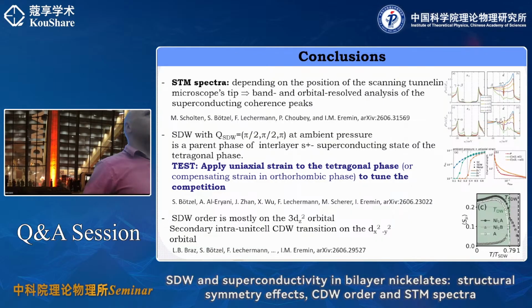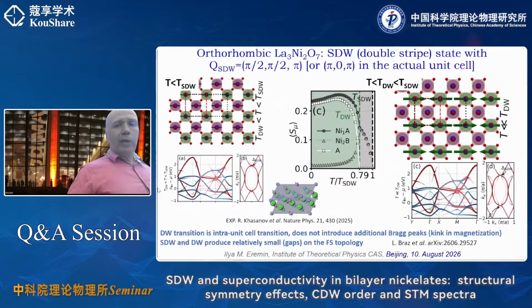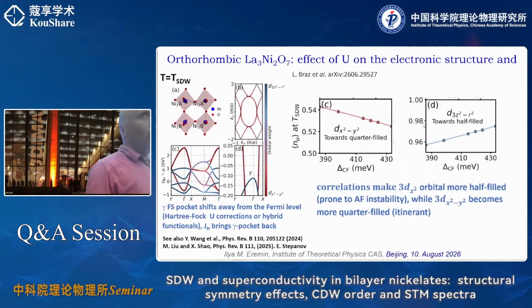But again, this is because, remember what I told you, and this is maybe something I can say, that this is more like a strong coupling picture: if you assume that the dz square is more localized, then of course you think that the main interaction is a super exchange. It's not in our theory, but if you try to make a picture of it, when you introduce the pressure, the layers come closer to each other. So the super exchange has to increase initially first. And this is why the transition temperature into the spin density wave state will go up.